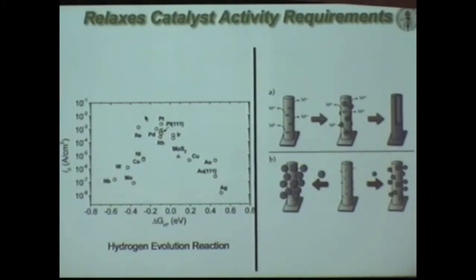And if distributed over this very high surface area, you relax the turnover number on the catalyst because it has to turn over less often since there's more area feeding the same total number of flux. And that means that if this is 3 orders of magnitude higher in surface area, you can satisfy the flux constraint with catalysts that are 3 orders of magnitude less active than platinum, like nickel or copper or cobalt or MoS2 and so on. And so we don't need the most active catalysts in order to have low overpotentials in principle to either oxidize or reduce water. So we can stay above our line in earth abundance without having in principle to develop new catalyst systems to do that.